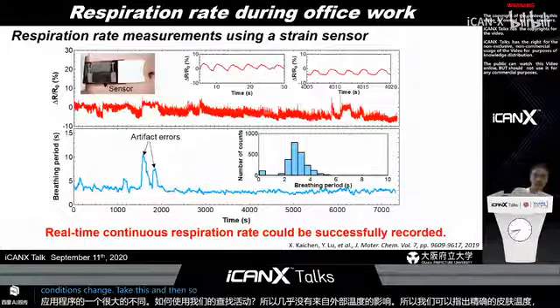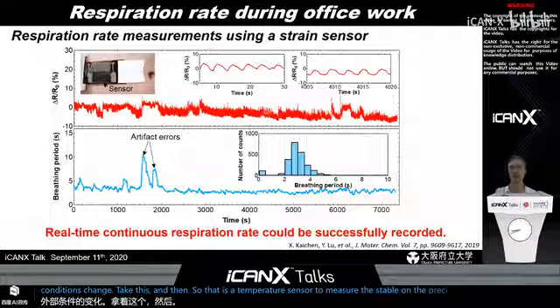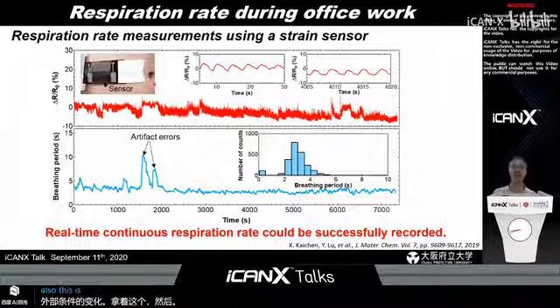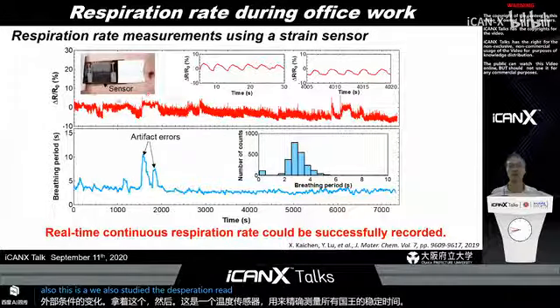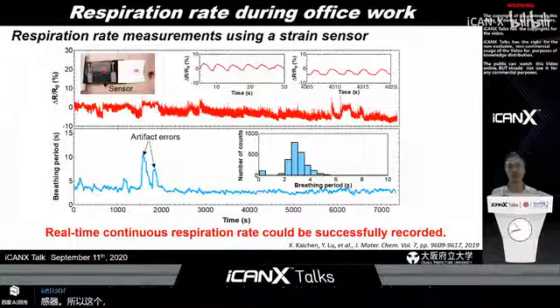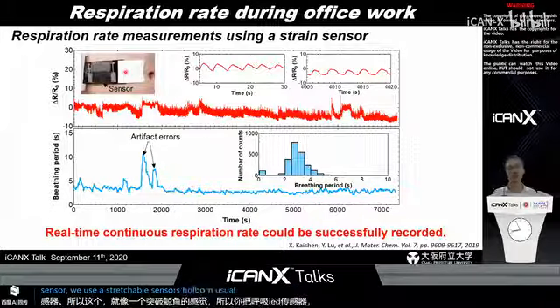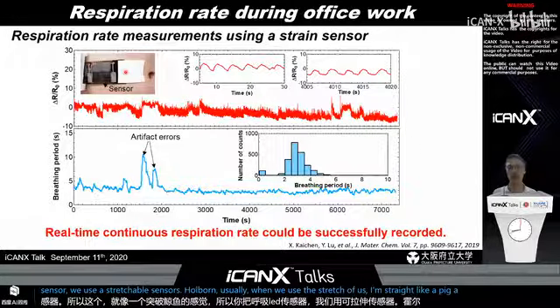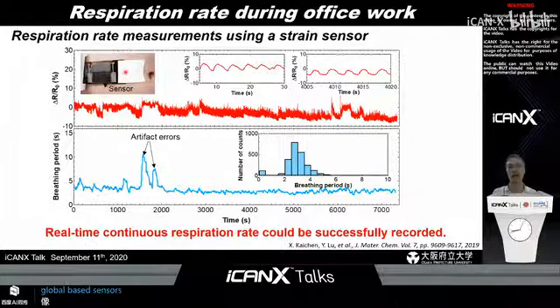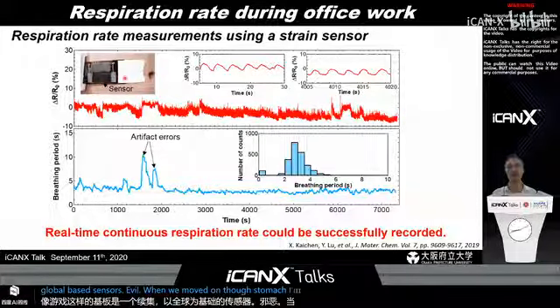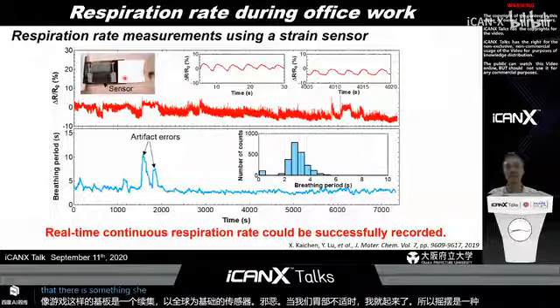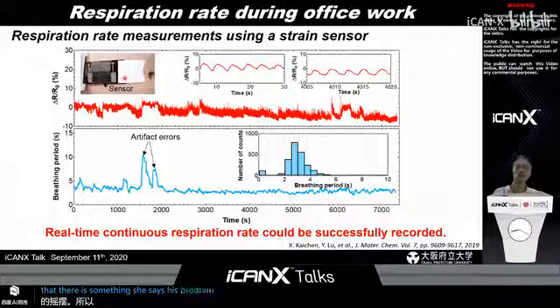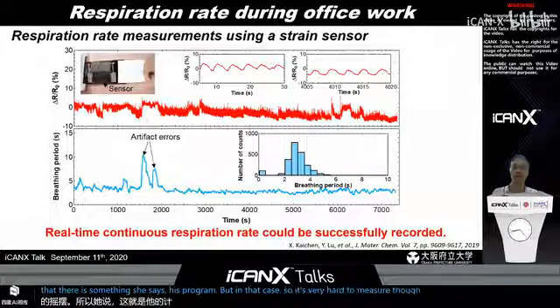And then, that is a temperature sensor for the stable and precise monitoring of the skin. And also, we study the respiration rate sensors. So this is like a breathing rate sensor. For the breathing rate sensor, we use stretchable sensors. However, usually when we use the stretchable substrate like PDMS or silicone rubber-based sensors, even when we move the stomach, strain is applied too much to the sensor, so that there is some hysteresis problem. In that case, it's very hard to measure the respiration rate stably.